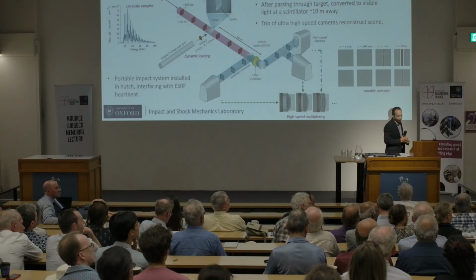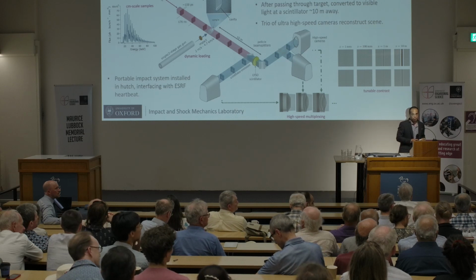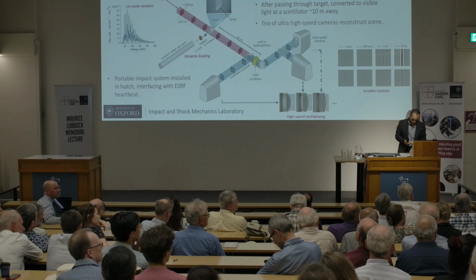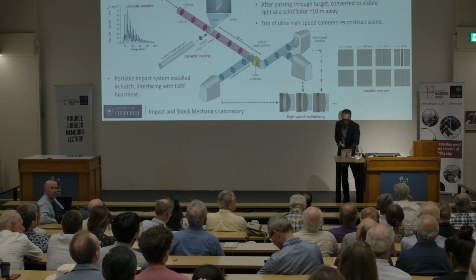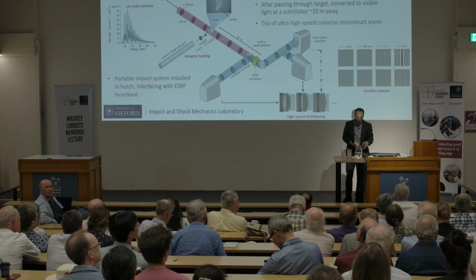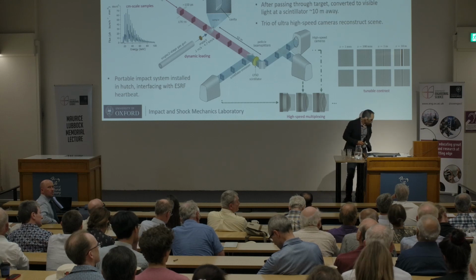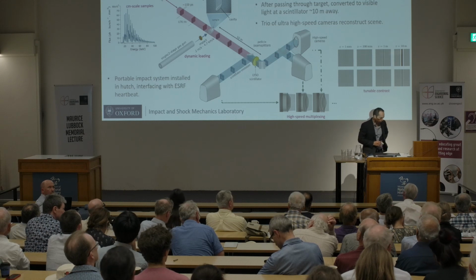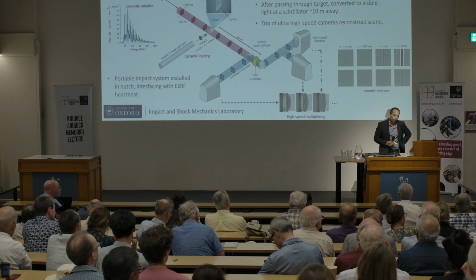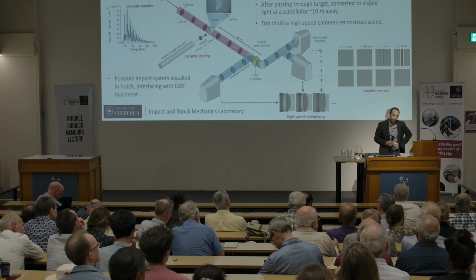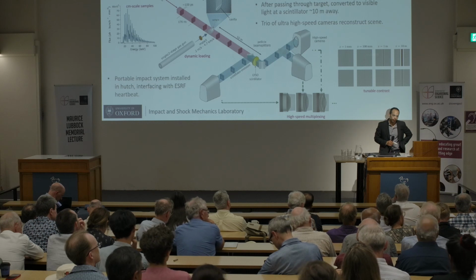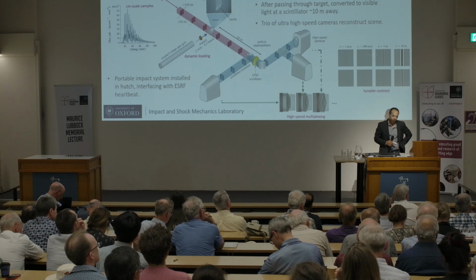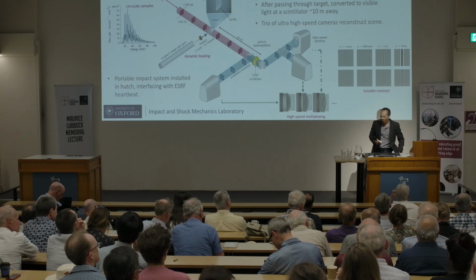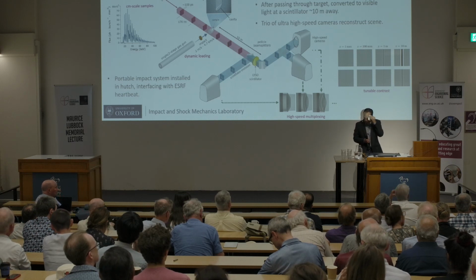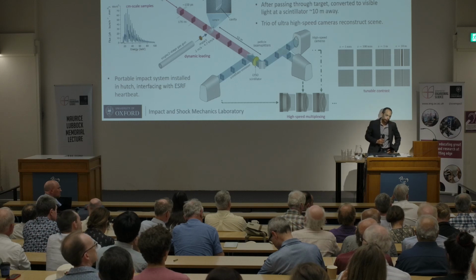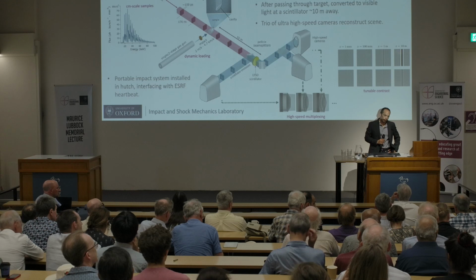Any comments from Constantino or Chiara? We have looked at modeling this numerically, but when you're using CFD, it's hard to model the effect that it has on the surface. We can model the jet, we can model the change of pressure, but we haven't coupled it on the fly with what happens to the material. We can take the pressures as an output and implement them as an input to a different type of software that can account for mechanical changes to the material, and I think that's really nice work. And we have done the droplets that I kind of skipped, which was very interesting to see, up to 500 meters per second hitting a surface and trying to visualize inside.